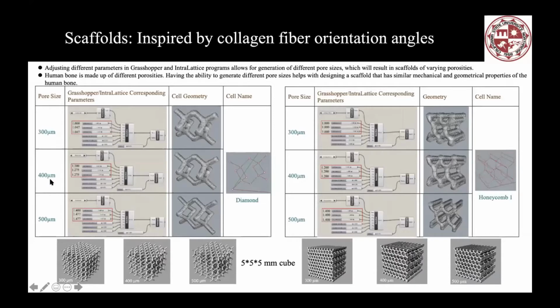We investigated different literature reviews, and based on the different studies they have done before, we found the effective porosity. I think it's from 200 to 900 microns. And then here we just choose 300, 400, 500 as the three basic parameters for the pore size.